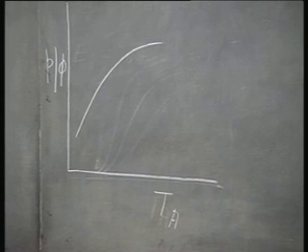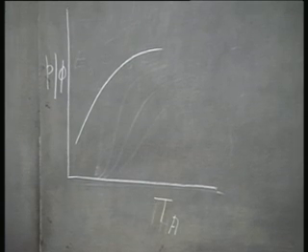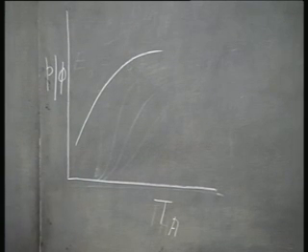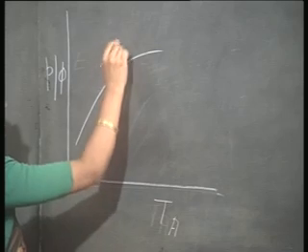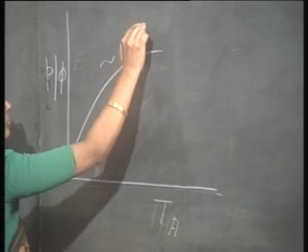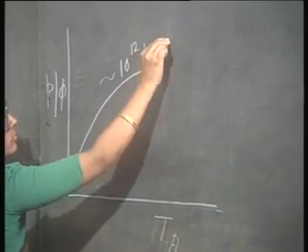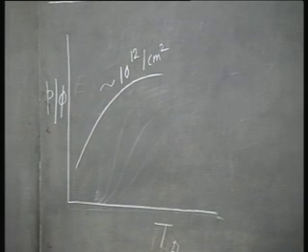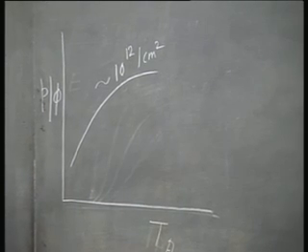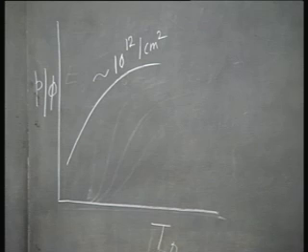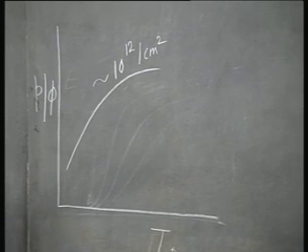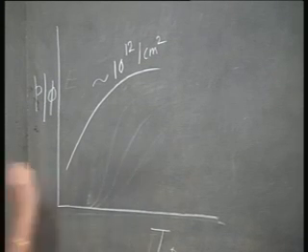Everybody is agreed, right? Well, this really happens when the dose is comparatively low, of the order of 10 power 12 per centimeter square, say 5 into 10 power 12, for example. If however, you go to higher doses, then you begin to find a very funny situation.